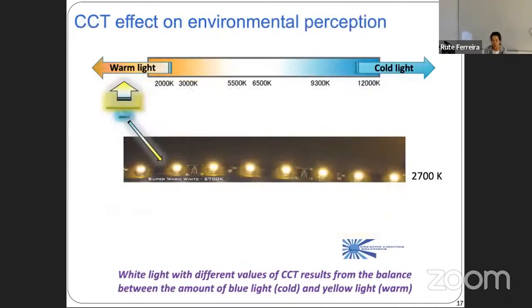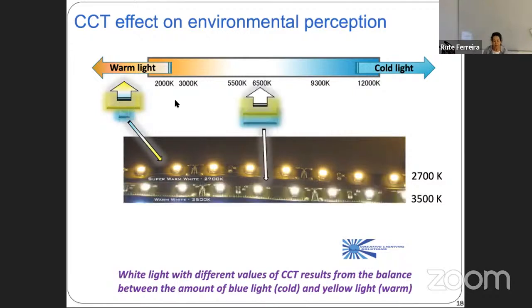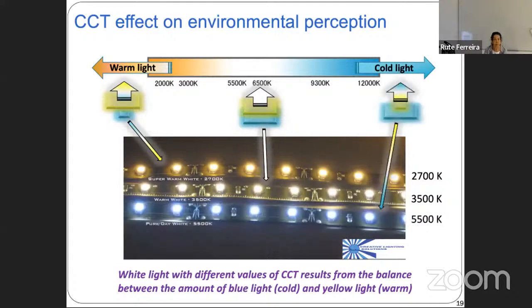So how is this managed in artificial light? White light with different values of CCT in fact results from the balance between the amount of blue, cold light, and yellow, warm light. Here I show you some LEDs with a low CCT value, in which we have a larger portion of yellow phosphor emission compared to the blue one. If we increase the relative amount of blue with respect to the yellow, we can see that there is an increase in the CCT. And finally, if the blue color dominates, the CCT increases to the corresponding value.